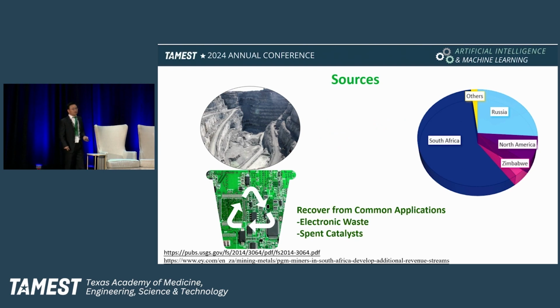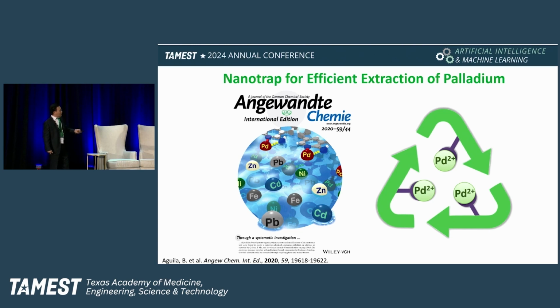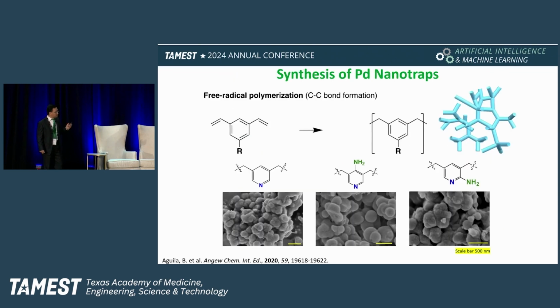We just use it to recover from the microelectronics and also from the spent catalyst, which can save us a lot and reduce the risk. So then we can design this palladium nanotrap to efficiently and effectively extract and recover the palladium from the spent catalyst, also from the microelectronics. So this is the part we designed.